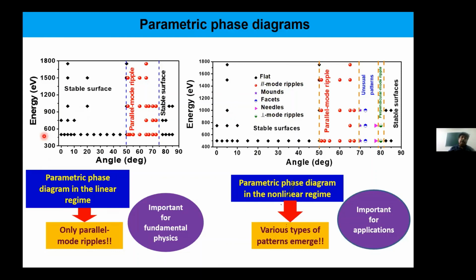Along the y-axis is the ion energy, and along the x-axis the ion incident angle, which was varied from 0 to 85 degrees or so for all the energies. For each incident angle value, for the same energy, we get to see different surface morphologies, and this is what he has evolved here in the form of what we call a parametric phase diagram for this pattern formation.